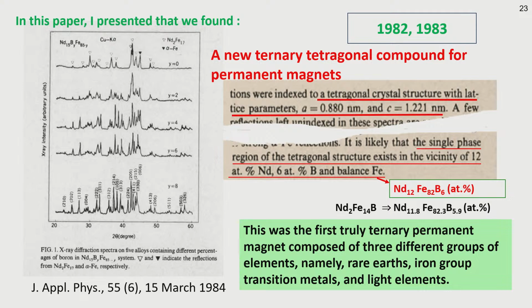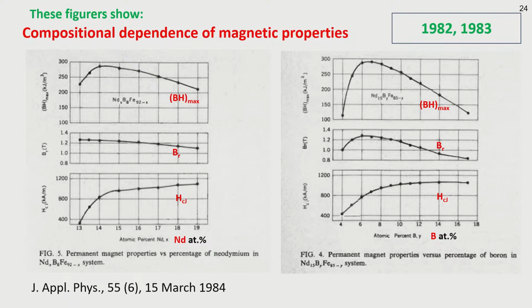And this was the first truly ternary permanent magnet compound of 3 different groups of elements, namely rare earths, iron group transition metals, and light elements. And these figures show compositional dependence of magnetic properties. On the left, neodymium content dependence. On the right, boron content dependence. And we determined 15% neodymium and 8% boron. This composition, neodymium 15, boron 8, iron 77, we determined this composition as the core of the new product called NeoMax.